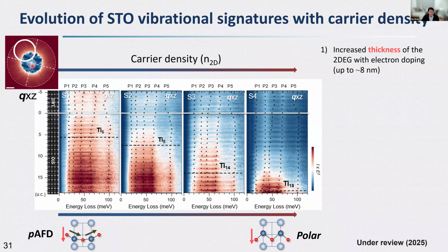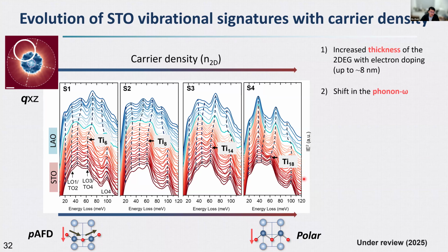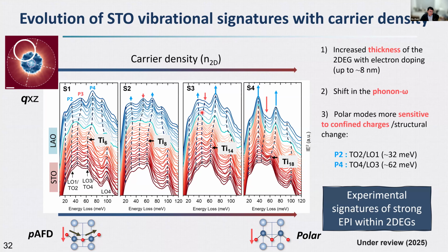You can see that with the increase of the carrier density, we see this change of the spectroscopy data. We don't need to worry about the details, but you see that the changes progressively increase into the STO layer. And this is a strong indication that the phonon modes are affected by the charge carrier. And if we plot it by line cut, we can see the peak positions more clearly. You can see how it shifts from the bulk towards the interface, which is the green curve here.